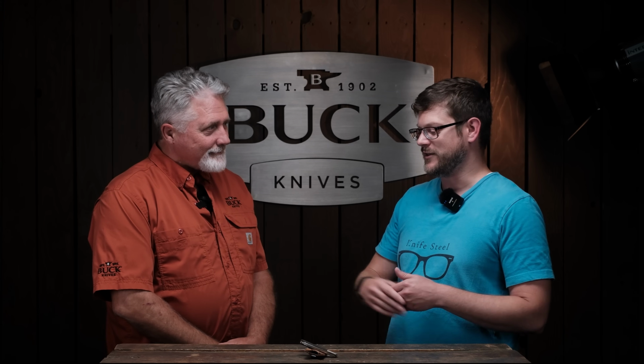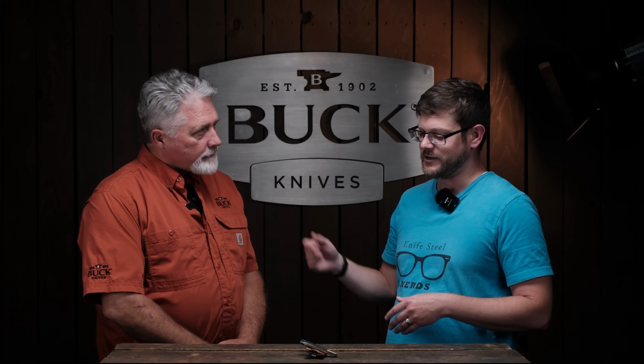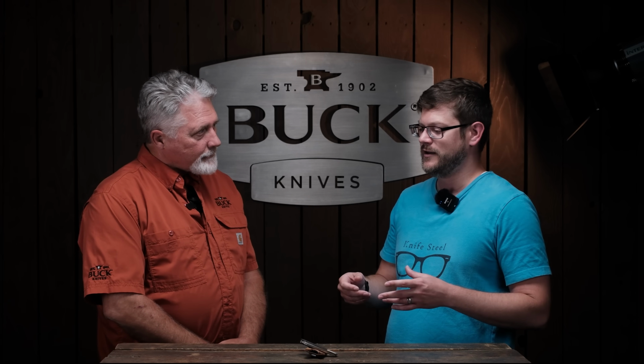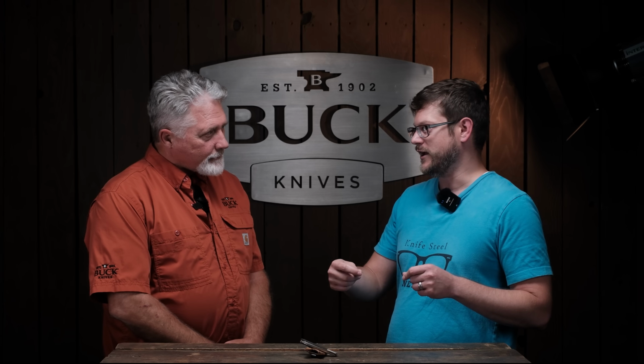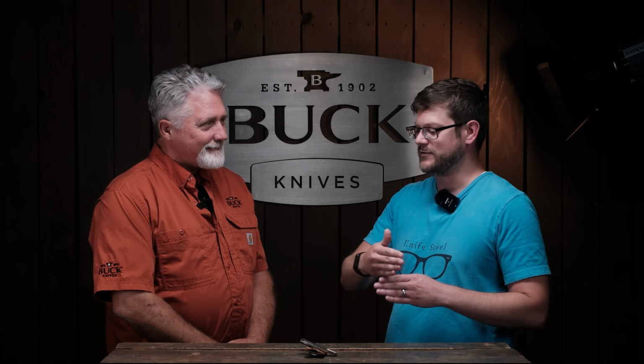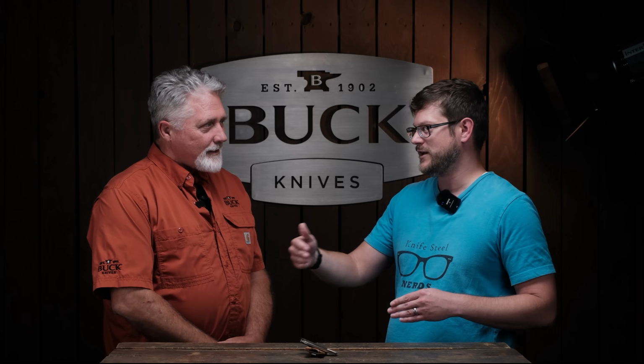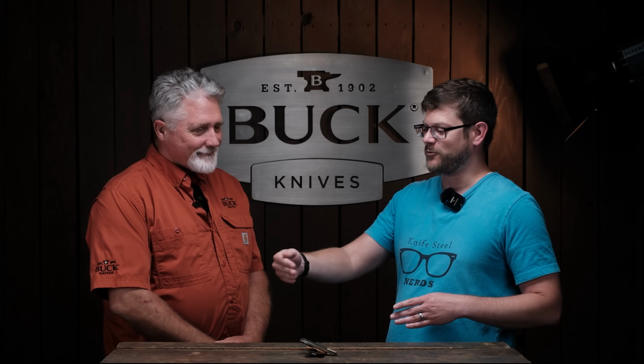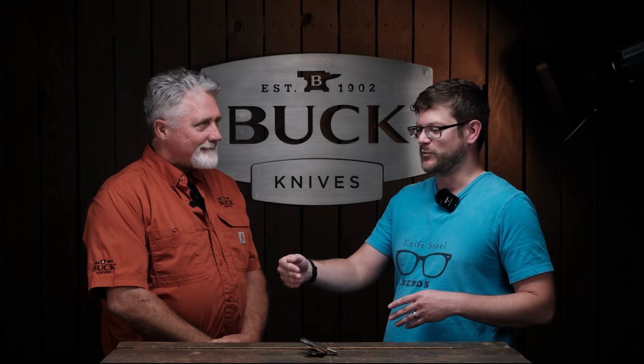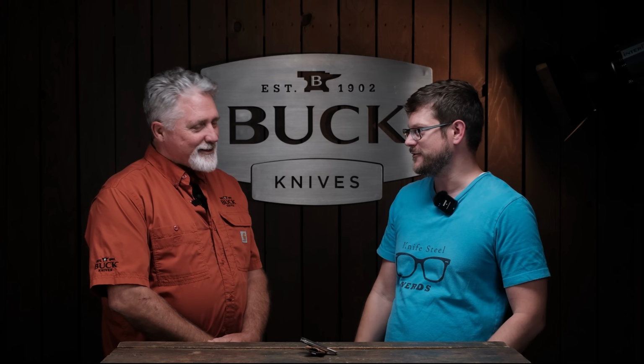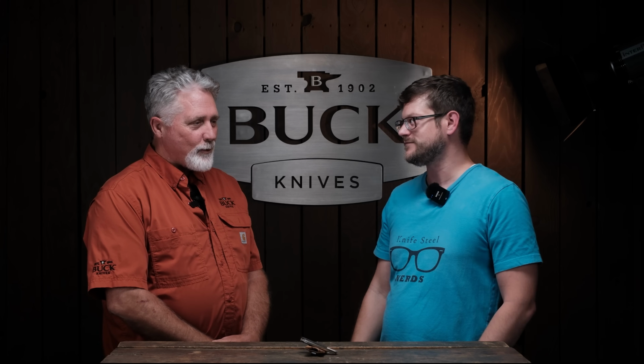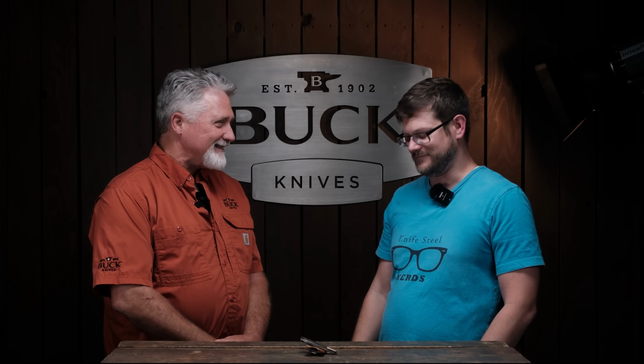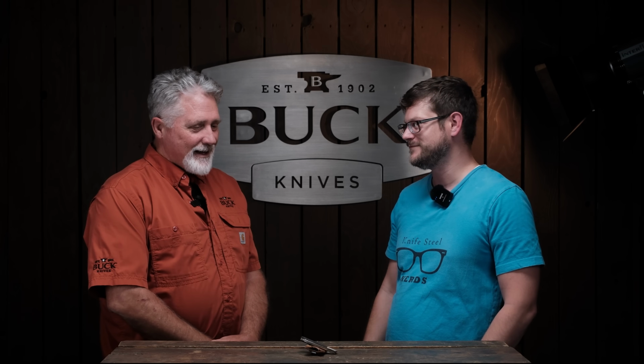So you're balancing things. Another element with manufacturing is that when you are grinding and sharpening, you can create heat in the blade. If you temper hotter, that gives you a little more factor of safety, because you can heat up to just about where the tempering temperature was before you start to change the properties. It's interesting. I've seen that go both ways, where we work harden and then we work anneal. I've seen it.